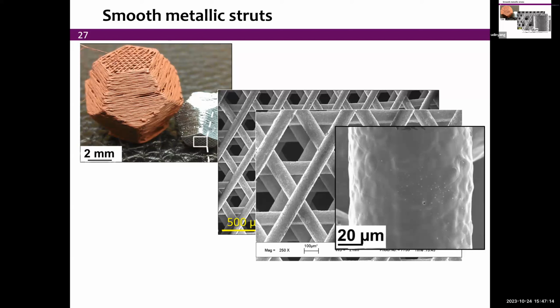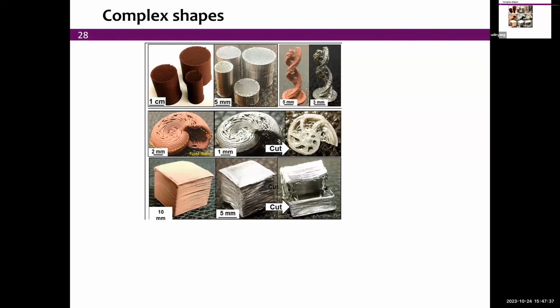If you try to do this with a laser, the laser track might be actually almost that thickness, you get extremely rough surfaces and therefore problems with fatigue resistance. So this sintering of sub-micron in situ created metal particles from oxide allows us to achieve very, very good surface quality. So a quick few examples.